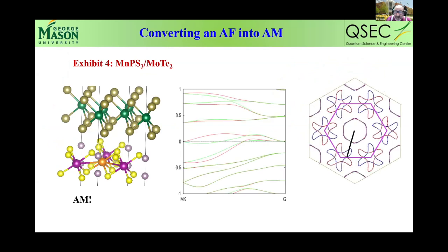Another example is gating, and 1 volt per angstrom is a large but not impossibly large gating. Then again, you get something similar to that. And the last one, you can do bilayer epitaxial contacting. I selected molybdenum ditelluride here because they have essentially exactly the same lattice constant matching, and then you get a really strong effect, dramatically strong effect. It becomes altermagnetic, also with some charge transfer in a very interesting way.